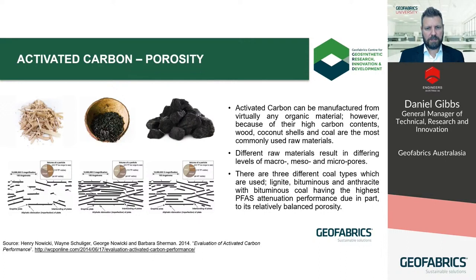Different donor raw materials and to some extent different processing techniques result in different properties in the final product, such as specific surface area and porosity. Now, porosity for these products is categorized in terms of their differing sizes, from tiny micropores less than about 2 nanometres in diameter, through to mesopores, which are between 2 and 50 nanometres, and macropores above 50 nanometres.